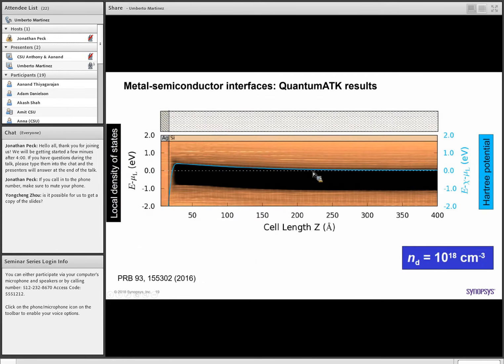I show this picture, which is very similar to the previous one, because it's for a lower doping density. Lower doping density means that the depletion region that we just mentioned is very long. So you see that in this case, it goes even about 20 nanometers. So you can immediately understand why you cannot really simulate this type of interface with just a few atomic layers, especially on the silicon side, which is the semiconductor side. So that's a critical point, that you really need these long devices, which we can treat fairly well with DFT.